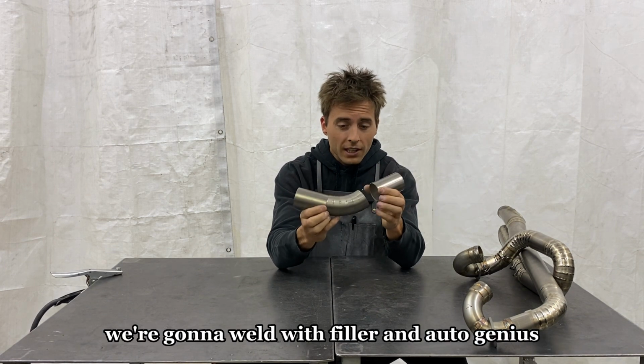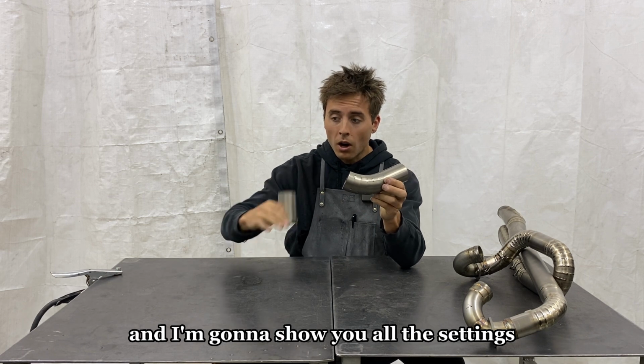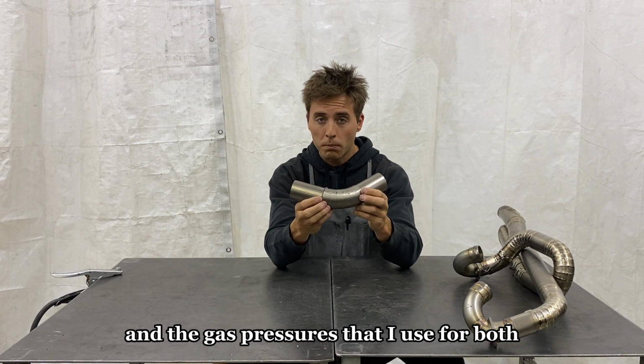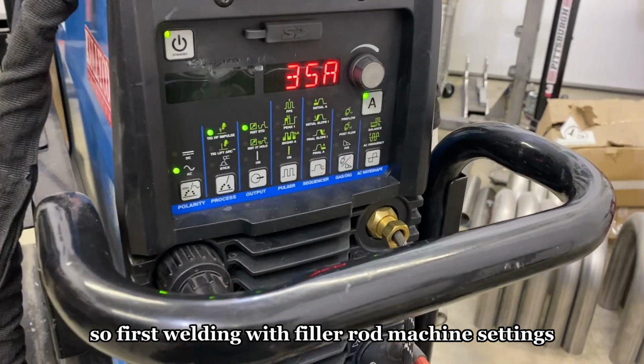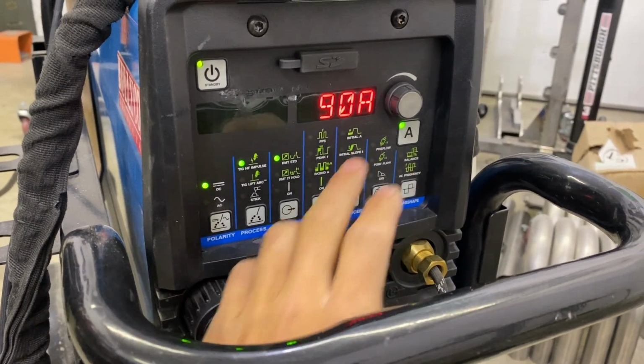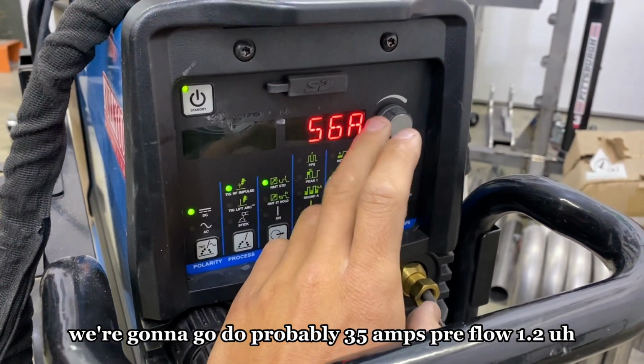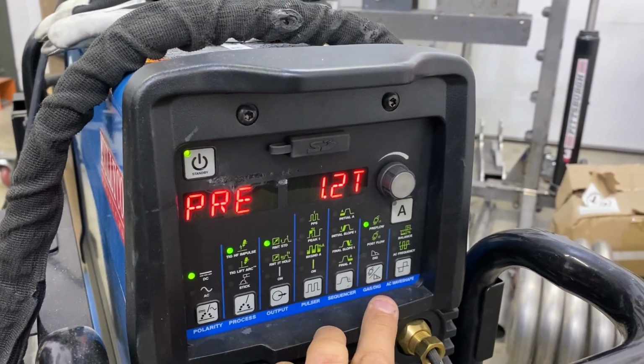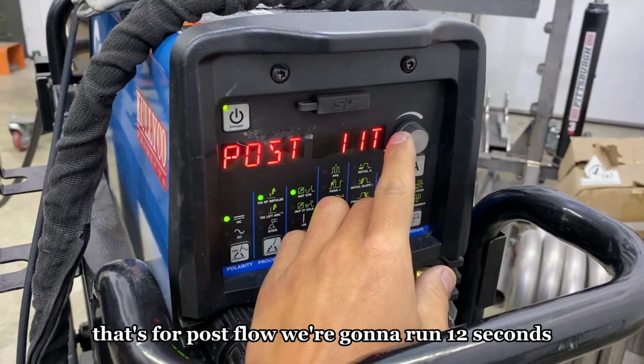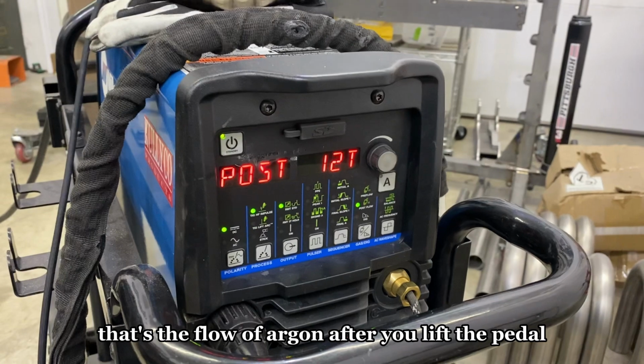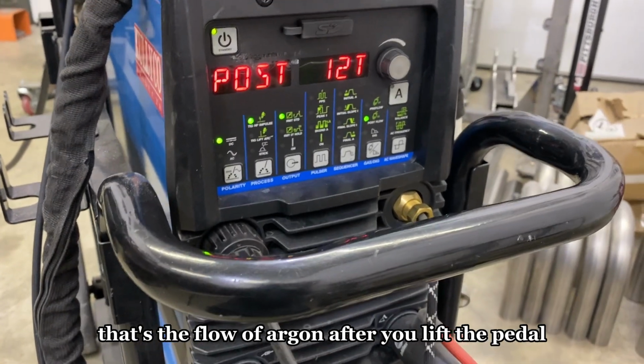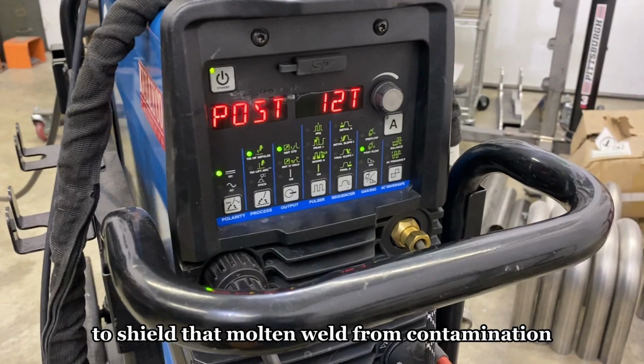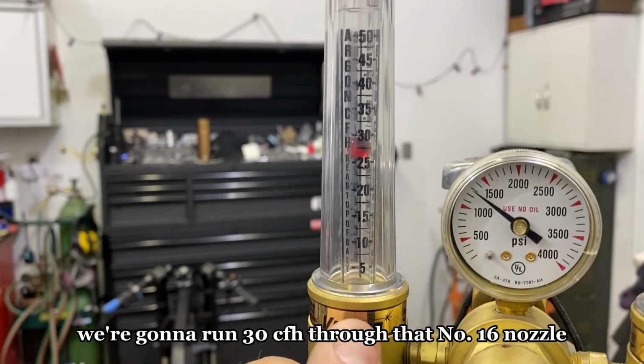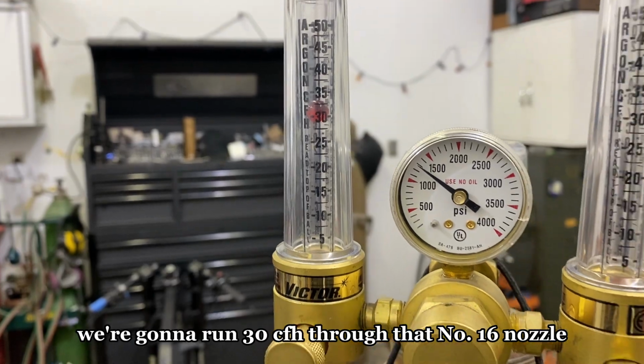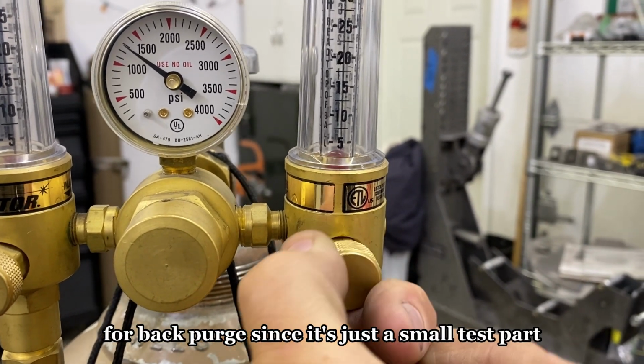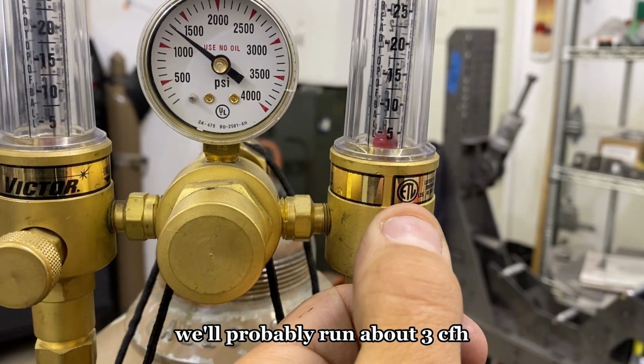We're going to weld with filler and autogenous, and I'm going to show you all the settings and the gas pressures that I use for both. So first, welding with filler rod, machine settings. Of course, you're going to want to be on DC. We're going to go to probably 35 amps. Pre-flow 1.2. I keep it here for basically everything. That's for post flow. We're going to run 12 seconds. That's the flow of argon after you lift the pedal to shield that molten weld from contamination. For gas pressure, we're going to run 30 CFH through that number 16 nozzle. For back purge, since it's just a small test part, we'll probably run about 3 CFH.